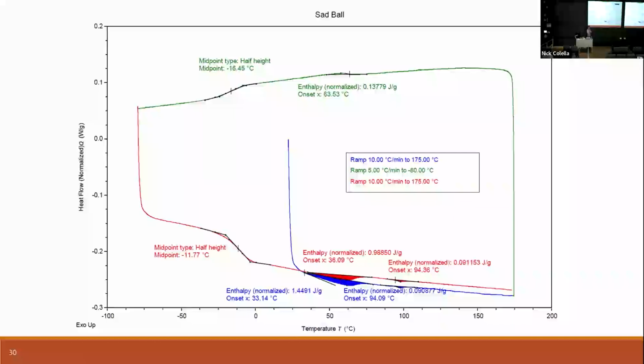In the rubbery state, we have more free volume. We have more energy in the system, it's warmed up, and now the chains can slide past each other. So you have more free volume, which means more room for energy to be stored, and therefore we have a larger heat capacity, which ends up being lower, further from zero on the graph that we have here. And we'll talk more about the glass transition and what happens when you're right at the glass transition when we talk about DMA.